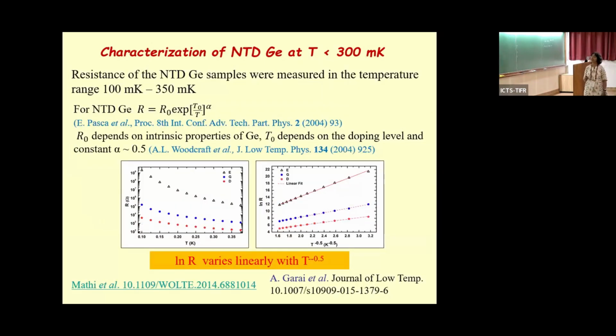Now you go and test it. As I said, the resistance is expected to vary as R naught exponential of (T naught by T) to the power alpha. Does the sensor actually behave that way? That's the first thing you want to check. R naught is a property of the material, T naught depends on the doping level, and alpha is nearly 0.5. We find that yes, indeed, the sensors we made from different batches of the germanium show different dopant levels. We get that, and we could make a good millikelvin thermometer.